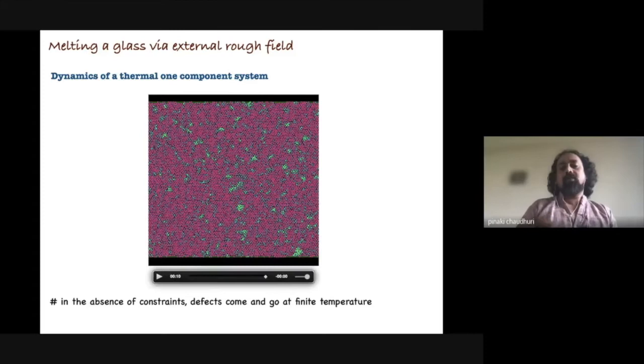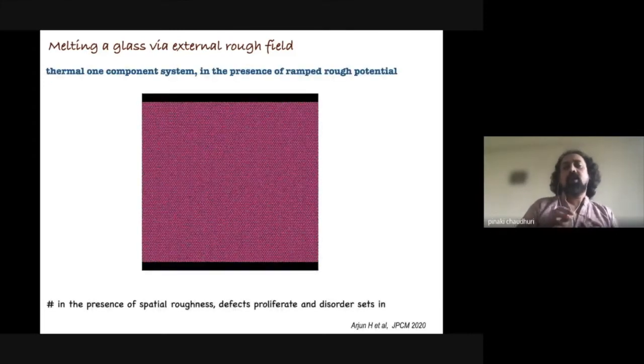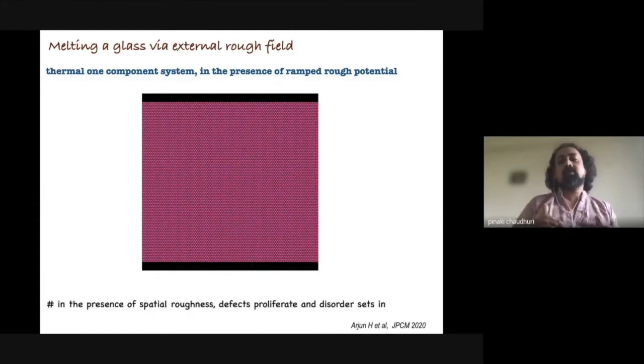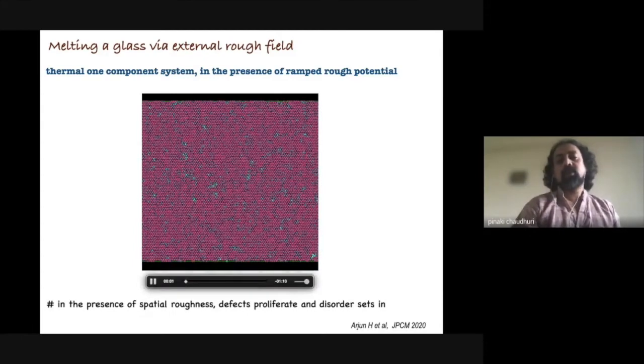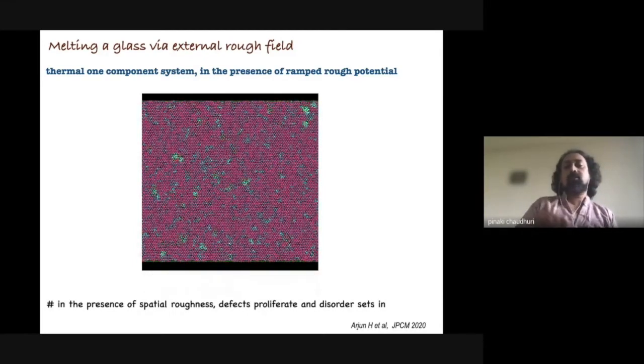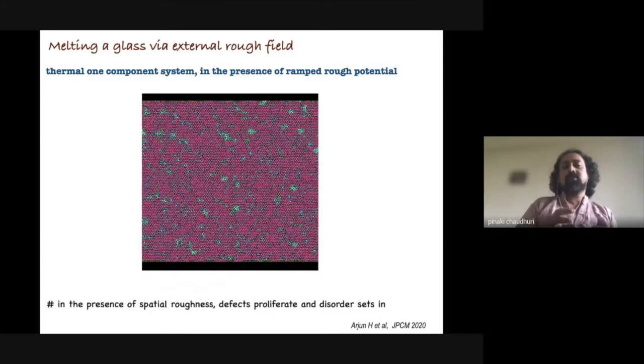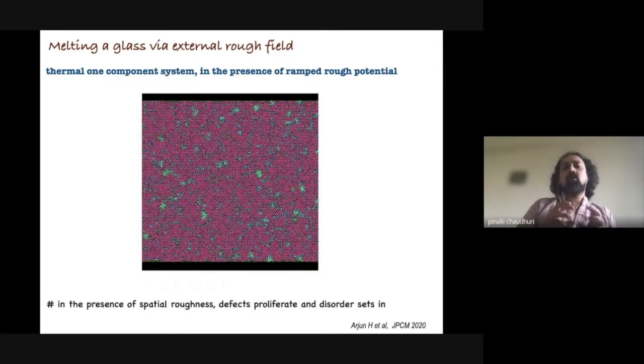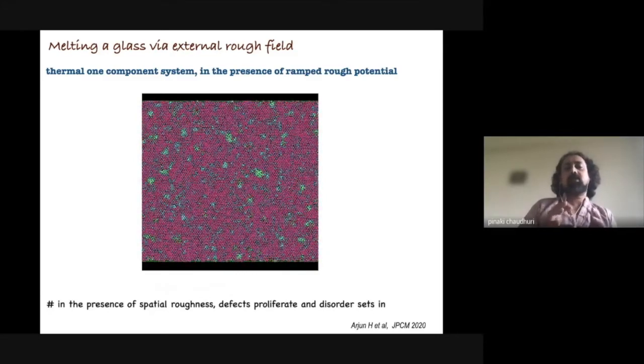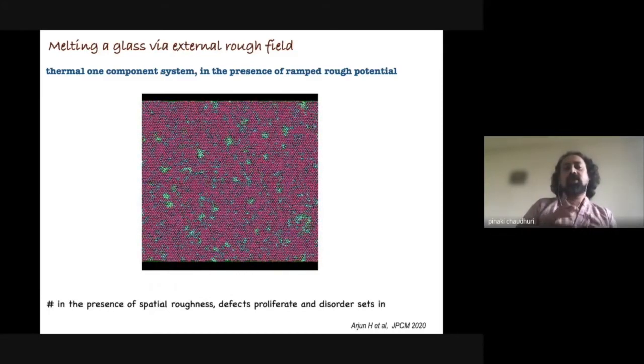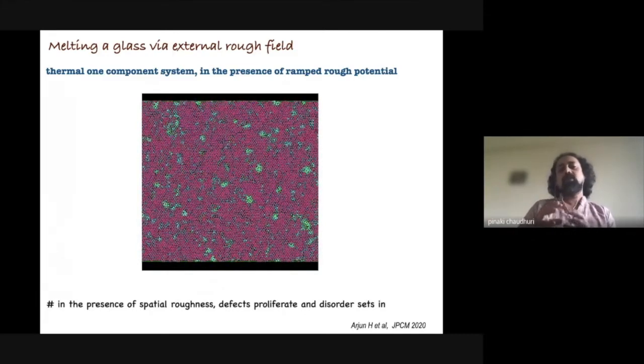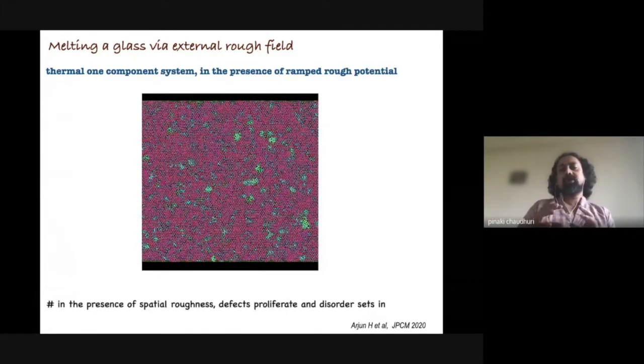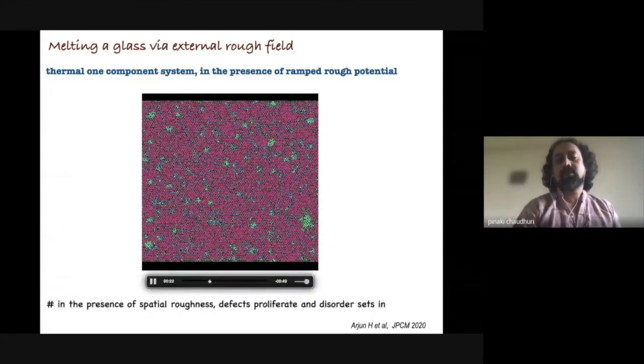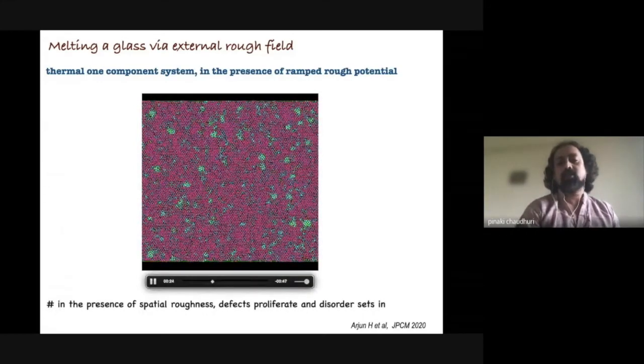Now, if I apply this external field, which is rough, and I increase the roughness of the potential as a function of time, then I can observe how this melting process is happening. So we are slowly ramping up the roughness of the external field. And these green patches that you see are patches where the hexagonal order or the hexagonal motifs are not present that much. You see that these domains of green patches, which are basically non-ordered or disordered regions, are proliferating in space, and eventually you will get a system which has large domains of disorder.